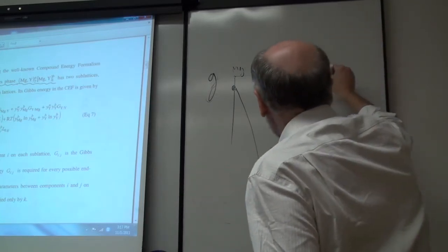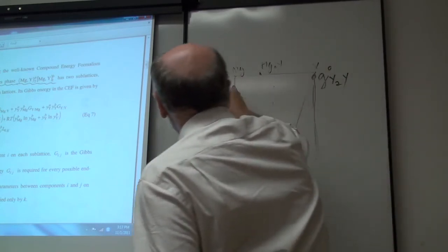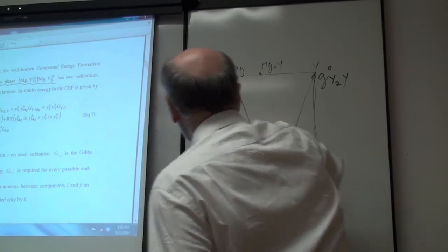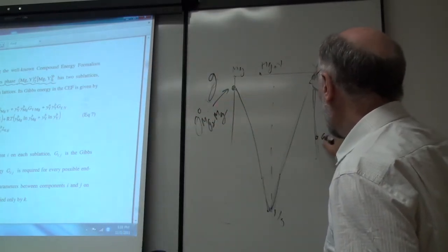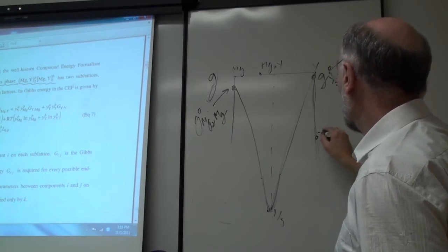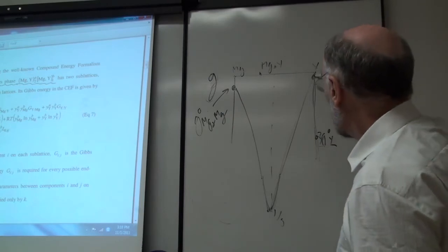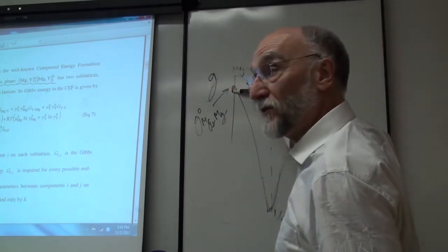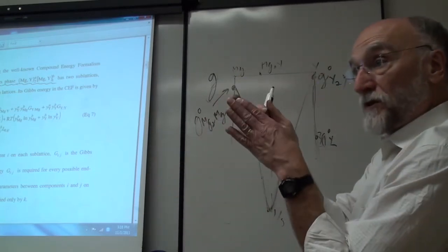This point up here, this is your G naught of Y2Y. This point here is your G naught of Mg2Mg. Your real Gibbs energy of real yttrium might be down here. This is the Gibbs energy. This distance then is the energy to form the defect. The further you put these up, the narrower your single phase region is going to be.